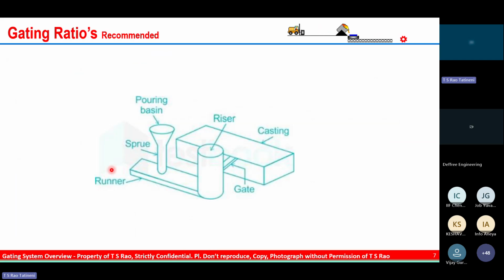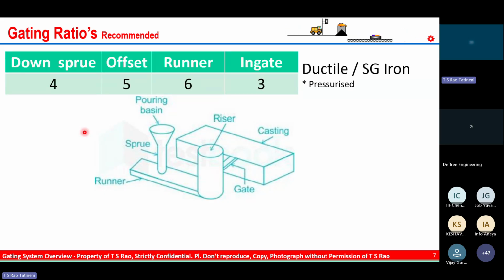And this is very important. The gating ratios are very, very important. Whatever formula you use for calculating the in-gate, the gating ratios are very important. So the top table is for the typical ductile iron pressurized gating system. So down sprue is to offset, is to runner, is to in-gate. This is very important. Most of the foundries ignore the offset, but according to me, the offset is very, very important with respect to producing sound casting. So that's why I introduced this offset. Normally they say 3 is to 6 is to 4, but I say 4, 5, 6, 3. This is very important. I explain why the offset is important in the subsequent slides.